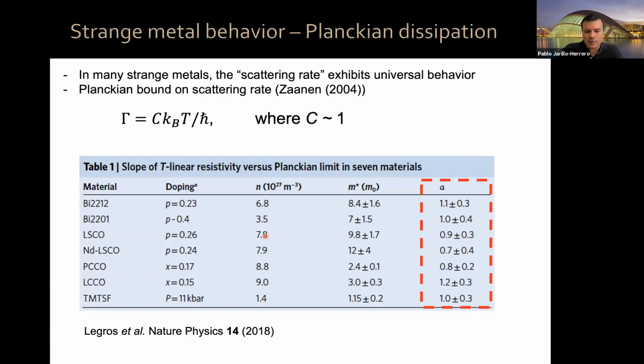Now, in a more recent paper, the group of Louis Taillefer studied this in detail for a variety of cuprate superconductors, and also compared with some organic superconductors. What they call alpha is what I call C here, the proportionality coefficient between the scattering rate and temperature, with the fundamental constants. As you see, it's not something that is perfectly quantized. It's not like quantum Hall physics, but it was seen to be within 30–40% of 1, for a variety of systems.